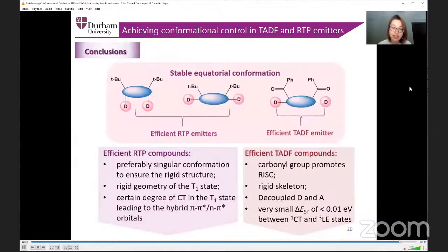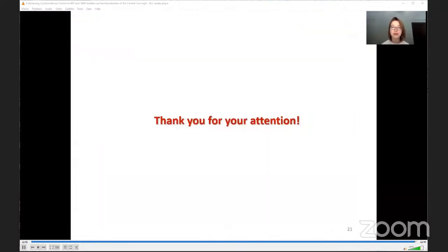Stable equatorial conformation, but also we were able to contribute to the existing design rules of this molecule. Thus, for the efficient RTP emitters, we are looking preferably for a single conformation and a rigid geometry in the T1 state with a certain degree of charge transfer, while for the efficient TADF compounds, it is useful to use the carbonyl group to promote the reverse intersystem crossing and a rigid skeleton. Thank you for your attention.